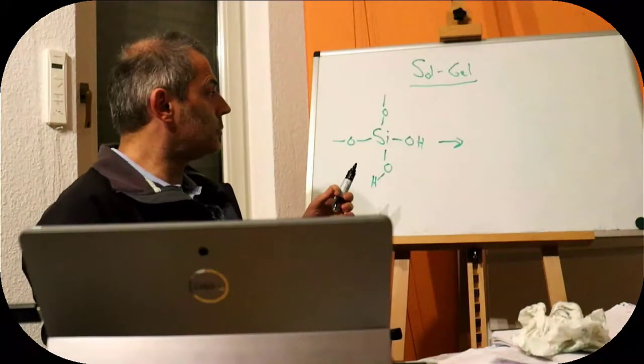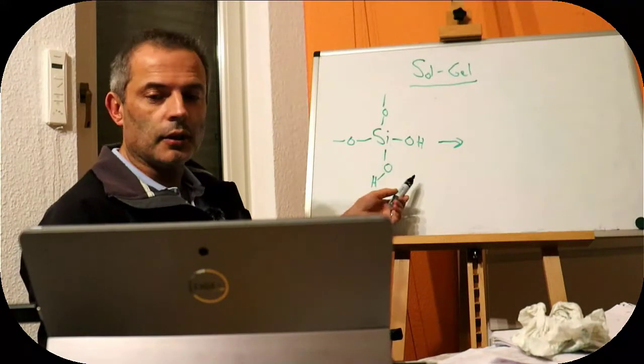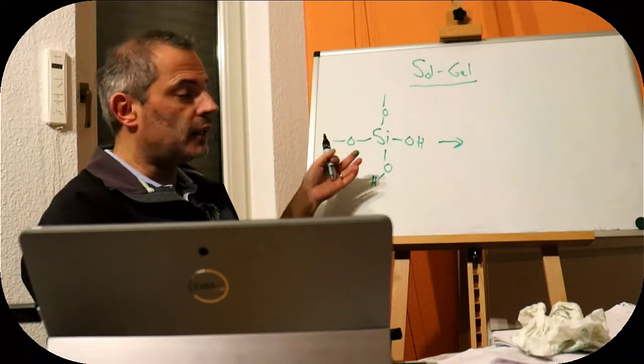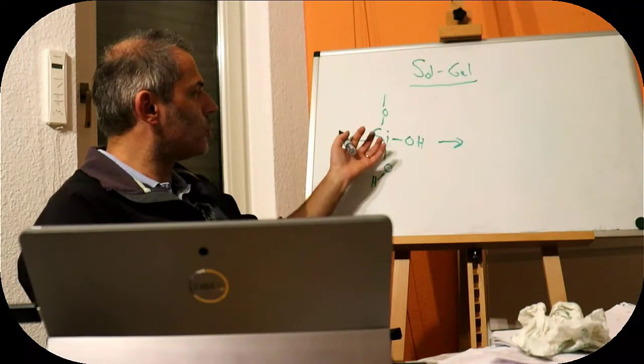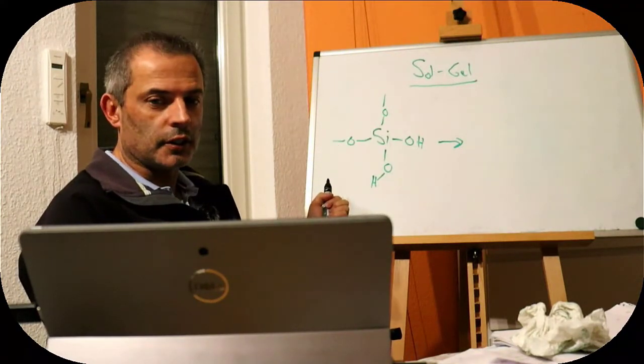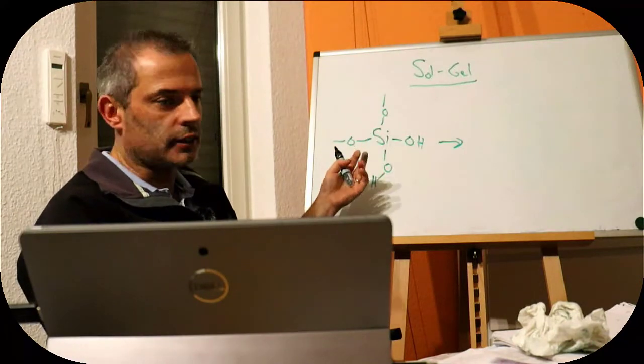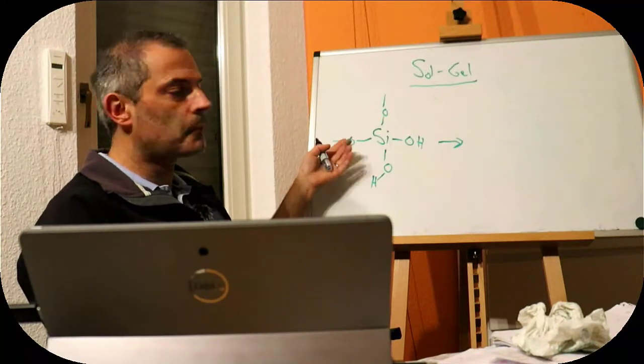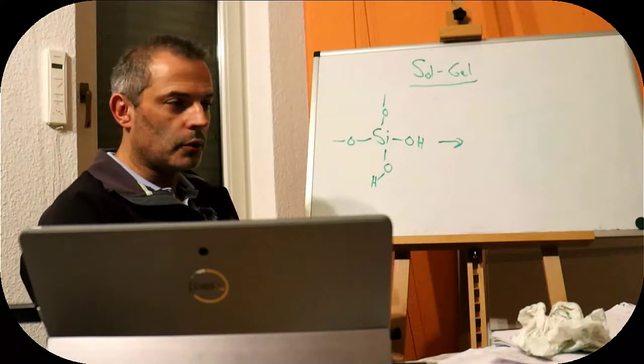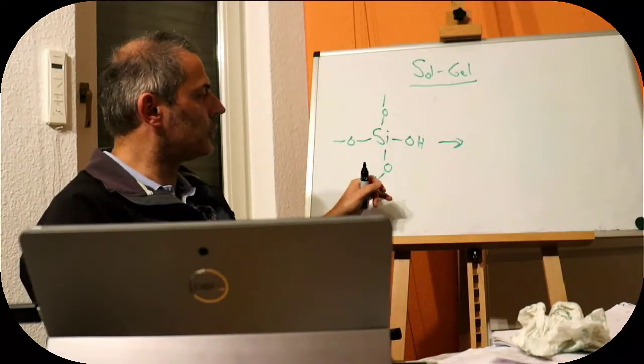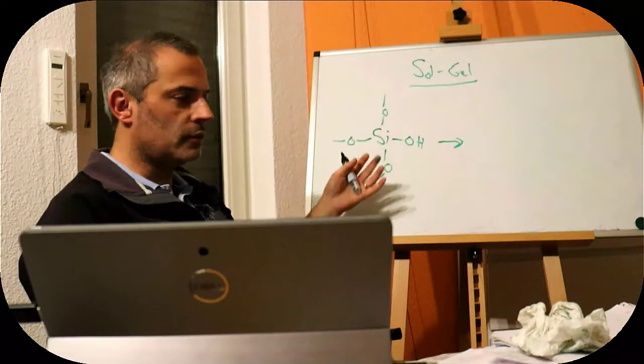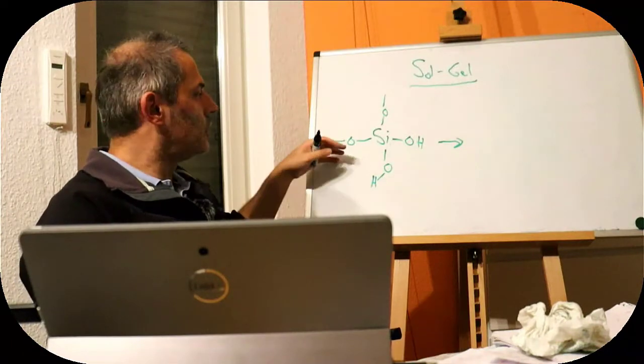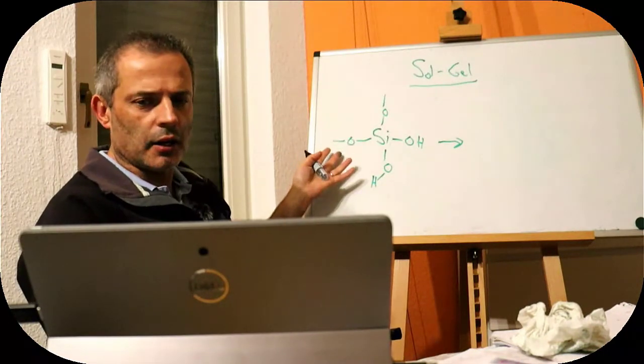There is a slight problem, however, as we increase the density of OHs on our silicon, we make it less and less reactive, because we're pulling the electron density away from the silicon, which makes it more negatively charged. These OHs are more electron withdrawing than these methoxy groups. So that's going to slow the reaction down. We'll typically take one off, and then take the next one off all of them, and we might end up with about here, about half.